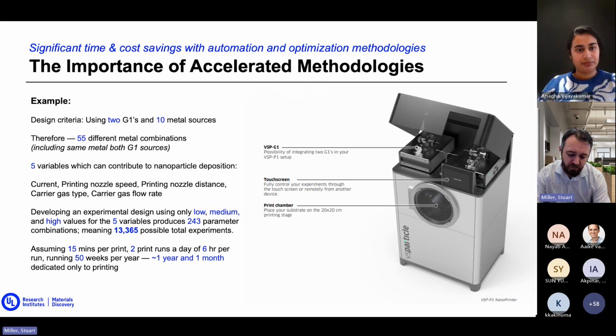We came to about 5 variables that we could manipulate: the current that we use, the printing nozzle speed, printing nozzle distance, the carrier gas type, and the carrier flow rates. There might be more. Some of these might be overkill, but it's just as an example that I'm giving here. And if we look at these 5 variables and we use a low, medium, high setting so that you can map out your full factorial DOE, it gives you about 13,500 possible total experimental combinations that you can look at on these 2 metals.